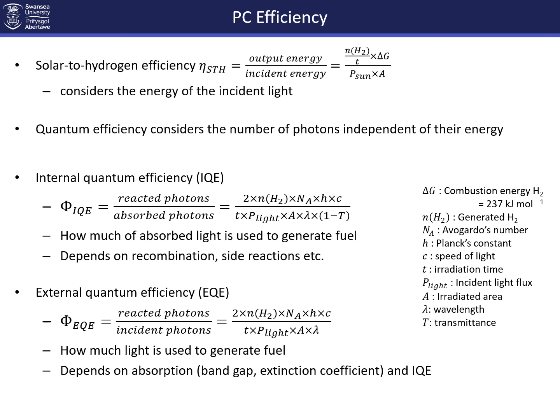The other type of quantum efficiency is the external quantum efficiency. So this takes into account not only the absorbed photons, but all incident photons. So it's a superposition of the internal quantum yield and the light absorption. So if all the light is absorbed, your internal and external quantum efficiency will be the same. If some light isn't absorbed, your external quantum efficiency is going to be lower than the internal quantum efficiency. But it's normally useful to determine both at the same time to give you a good picture of the limitations of a photocatalyst.